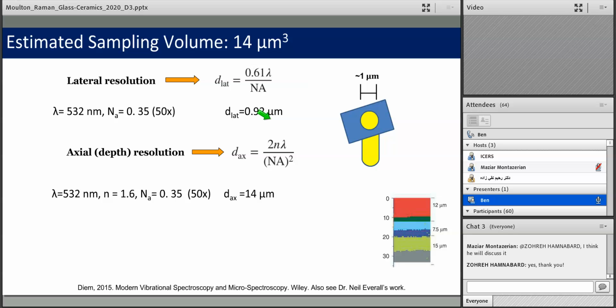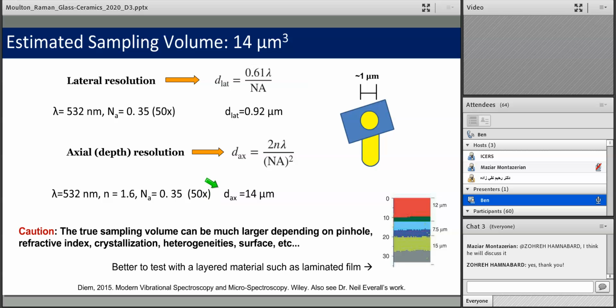But what that doesn't take into account is all the scattered light below the surface of the material. And to get that depth resolution, or the axial resolution, this is determined by 2 times n, where n is the refractive index, times the wavelength again, divided by the numerical aperture squared. So if we use the same conditions as our previous calculations, but on a glass that has a refractive index of 1.6, we have a vertical volume of at least 14 microns. I highly recommend that you put this information in your publication, but I warn you that this is a gross underestimate and that the true sampling volume, because of the scattering below the surface of the sample, is not actually a cylinder, but it's a cone, then it can be much greater than this volume.